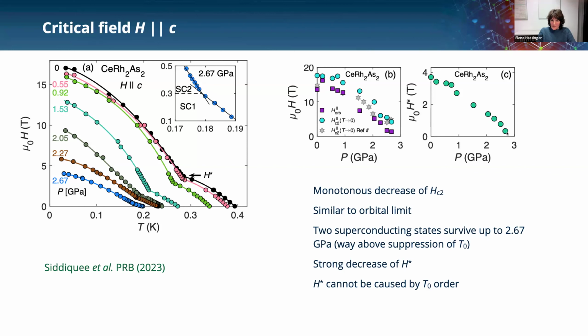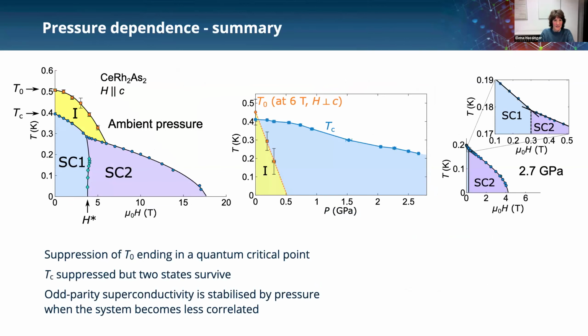Okay, so what we know from before is that T naught is suppressed at half a gigapascal, but the two superconducting states survive up to the highest pressure we measured, so 2.7 GPa. And this means that the T naught cannot be the origin of the H star transition, which is claimed by some of our colleagues.